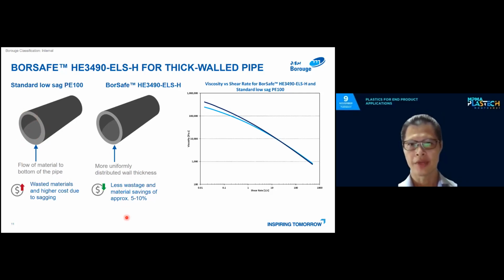With this new grade that we are introducing, ELSH extra low sag material, a more uniform distributed wall thickness can be achieved with ease and no wastage, saving about 5 to 10%. How is this possible? Because when this material exits the die, it has a higher viscosity compared to the standard PE100. So this material will resist flowing downwards due to gravity and is able to cool to form this uniform wall thickness.